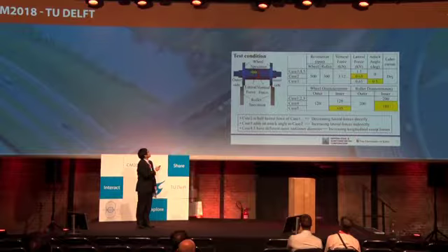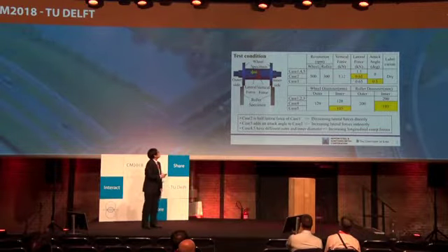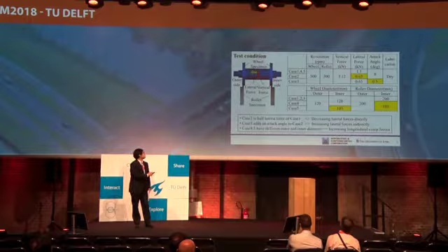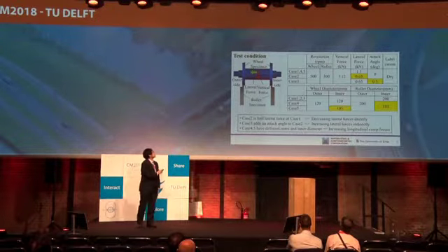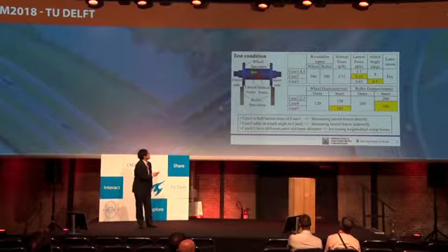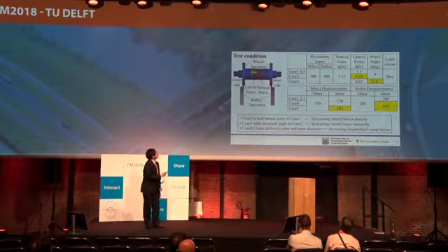And this shows the several test conditions. In this test, each wheel specimen is in contact with a roller specimen, and the wheel specimen is driven by the roller specimen. The roller side driving revolution is 300 RPM, and the wheel side driven revolution is 500.